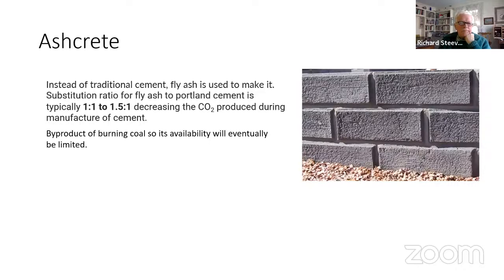So here's ashcrete. You use fly ash in making the cement, and I think that you can use a variable amount of fly ash when you're producing cement. Based on something that someone said to me, I haven't verified this independently, but my understanding is that Portland cement in the state of Wisconsin requires a minimum amount of fly ash, and that's because its composition includes a fair amount of a particular type of silica, and it's only certain fly ash that can be used in making this Portland cement.